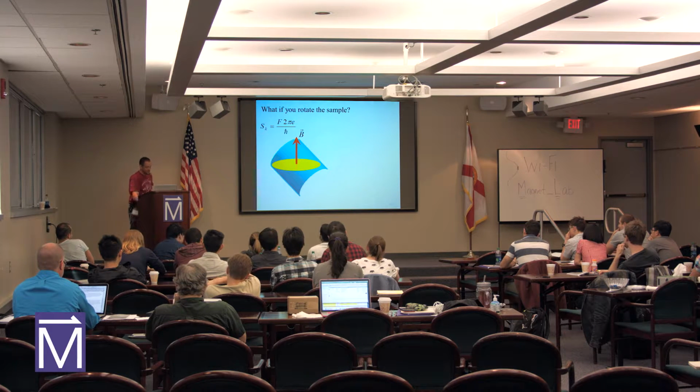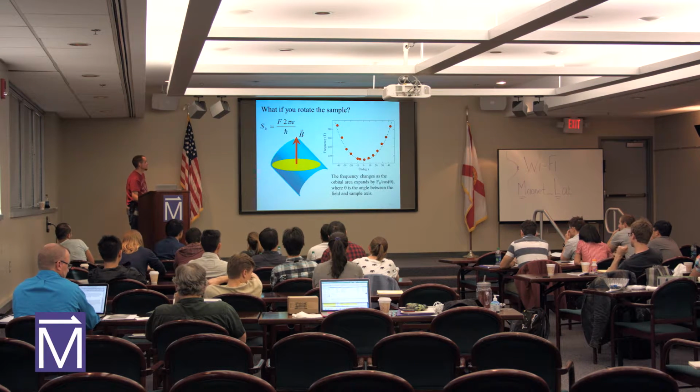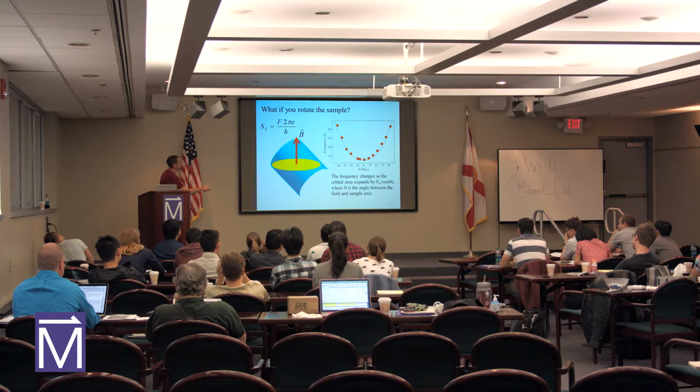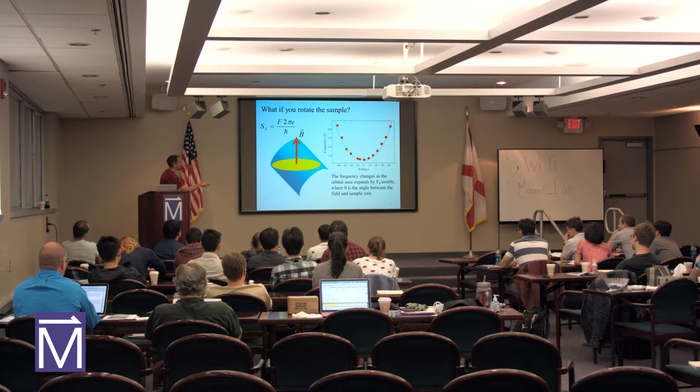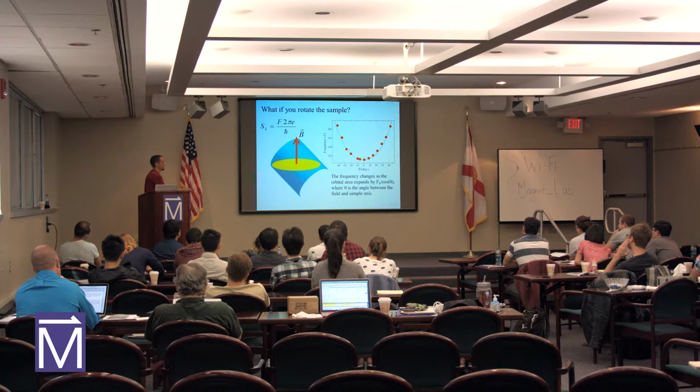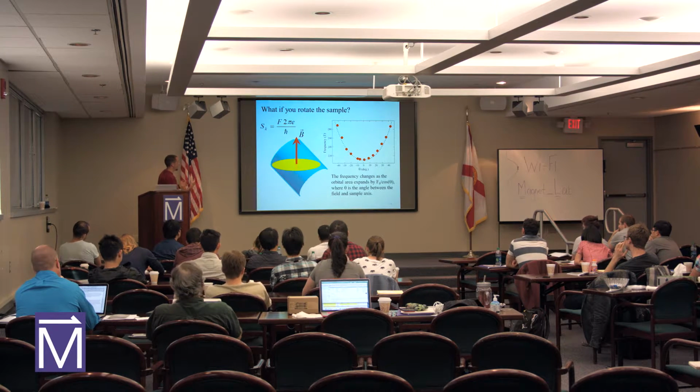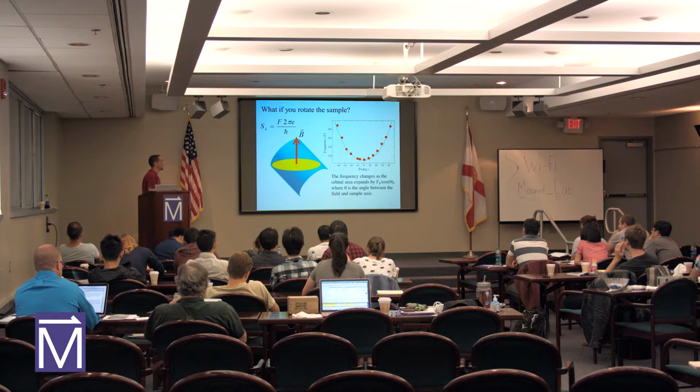So we usually plot our frequency versus the angle, and we get a relationship like this. When it's 0 and the field is directly along the cylinder, we'll get the lowest frequency. But as this area gets larger, the frequencies get larger as we move out an angle from that point. If it's a perfect 2-dimensional cylinder, it'll follow the smallest frequency over cosine theta. But of course, not every Fermi surface is a perfect 2-dimensional cylinder. Most of the time, they're not.